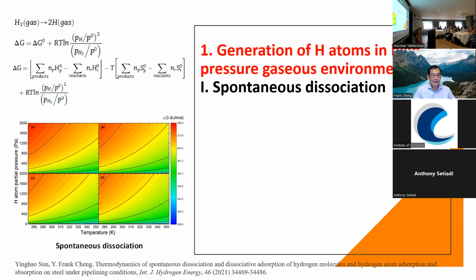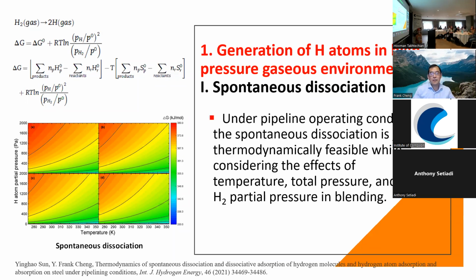You can see that under all the conditions, the free energy change of this reaction is positive. We know that if the free energy change is positive, this reaction is thermodynamically not possible. So based on the thermodynamic analysis, we have an important conclusion: under pipeline operating conditions, the spontaneous dissociation of hydrogen molecules is not possible. That's why we don't need to worry about hydrogen atom generation by this mechanism, because the thermodynamic calculation tells us the answer is no.